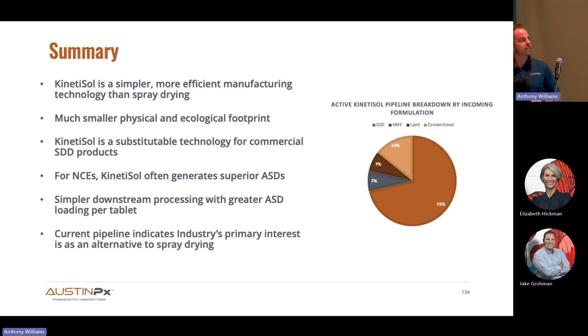There's two case studies where we showed where we think we're directly substitutable for commercial spray drying and can result in a bioequivalent product. And then for NCEs, we have the potential to provide much better performance than spray drying, just by virtue of different particle properties, but also by opening up a formulation toolbox that the other technologies don't have access to, so we can arrive at an optimized ASD composition. And then the easy part, simpler downstream processing, that's obvious.